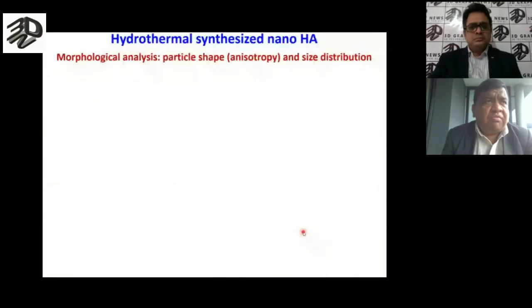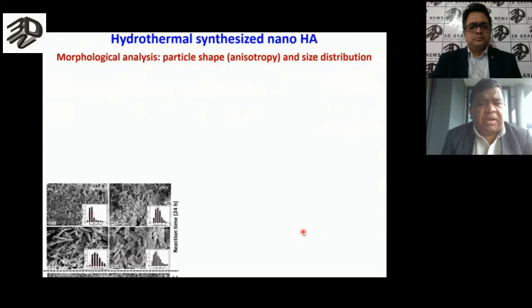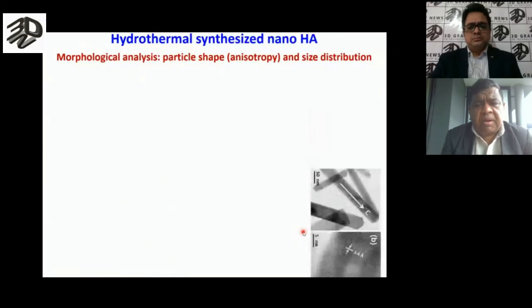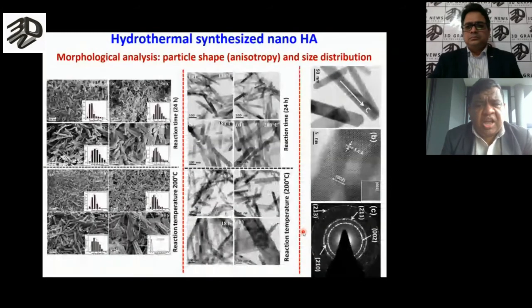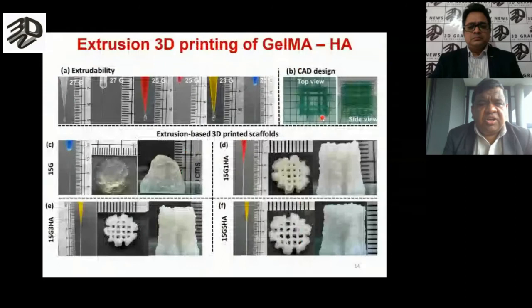For that we have used this hydrothermally synthesized nanohydroxyapatite. Now, I'm not going to spend much time on nanohydroxyapatite. Just to show you, we are able to achieve very fine nanometric hydroxyapatite with a width of less than 50 nanometers, and it has an aspect ratio of 9 to 10. It has hexagonal symmetry and so on.